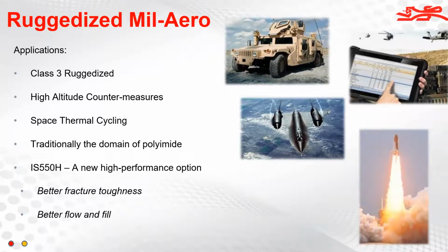And with a traditional polyimide type material, what you end up with in those heavy copper applications is you end up with these large clearance areas where you're filling all those clearances with this polyimide resin. And when you go drill through those clearance areas, you end up with fracturing. And we've actually seen a lot of cases where a designer really wanted to use 2 or 3 ounce copper, but because of the fracturing, they've had to design out that heavier copper, which really isn't what they wanted to do. With a material like the IS550H, you can go ahead and design with that 2 or 3 ounce copper because it's much easier to drill.